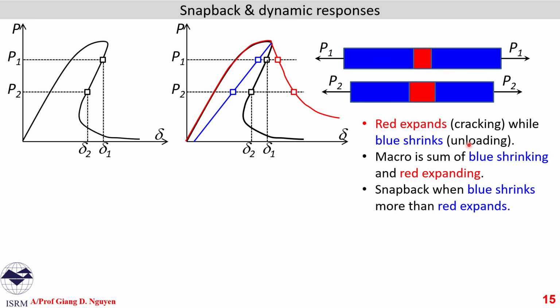And this is the one we may have in experiments. Say if we have a longer specimen, the blue zone is getting bigger, while the red zone is almost the same, because if they're of the same material under the same stress condition, then the fracture process zone is the same in these two specimens, the longer and the shorter one.